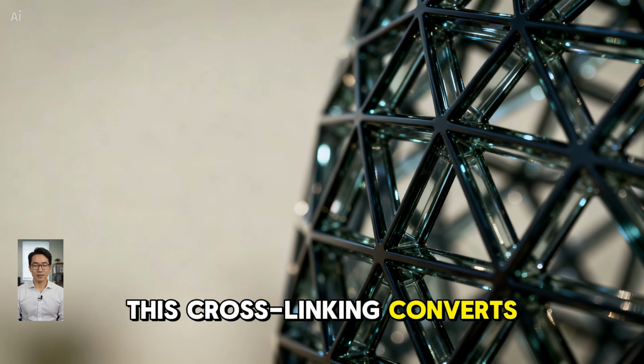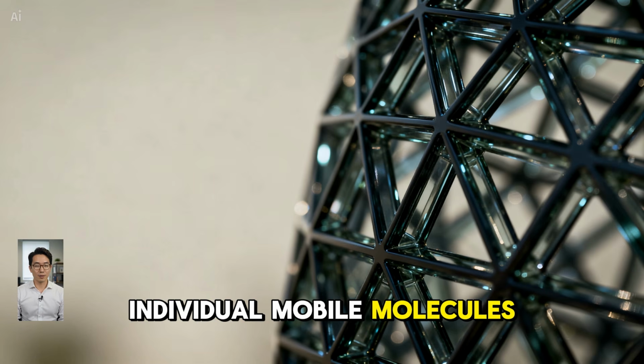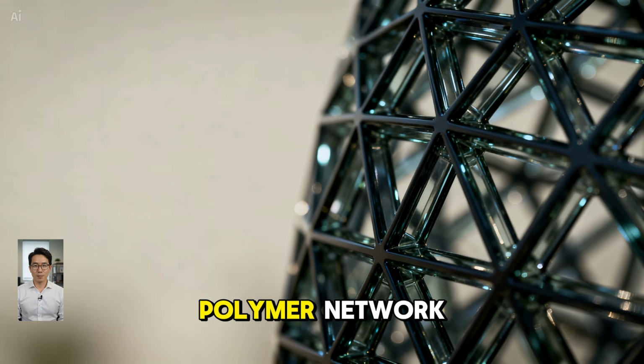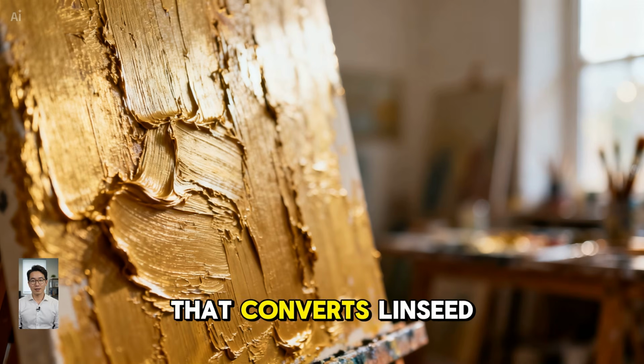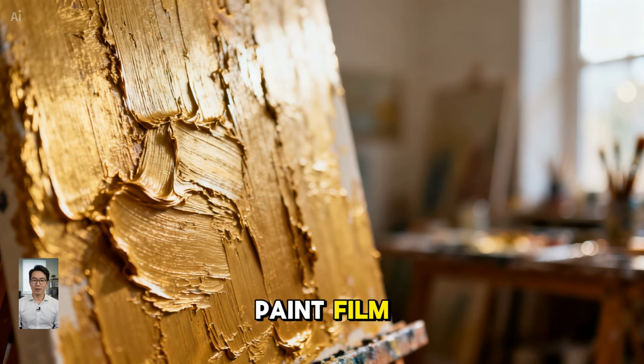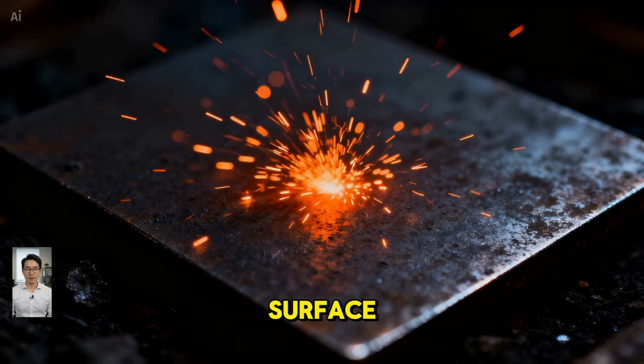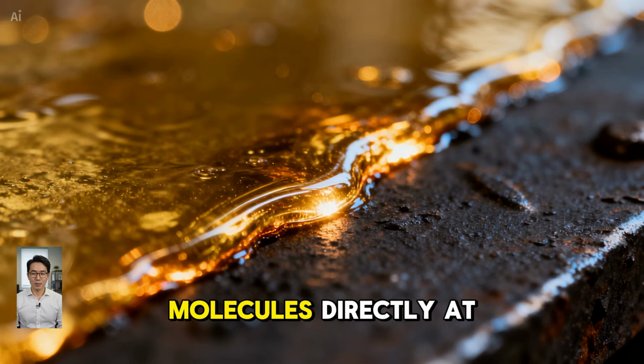This cross-linking converts the oil from individual mobile molecules into an increasingly rigid 3-dimensional polymer network, the same process that converts linseed oil in paint to a dry paint film. Second, the iron surface catalyzes this polymerization reaction. Iron ions at the surface of the pan act as oxidation catalysts, accelerating the polymerization of the oil molecules directly